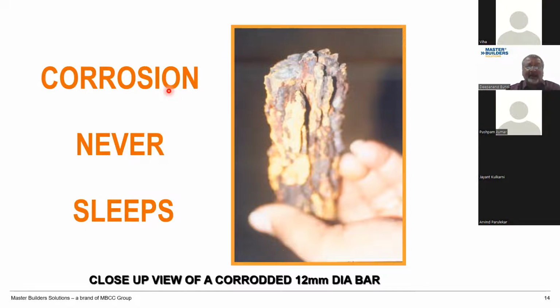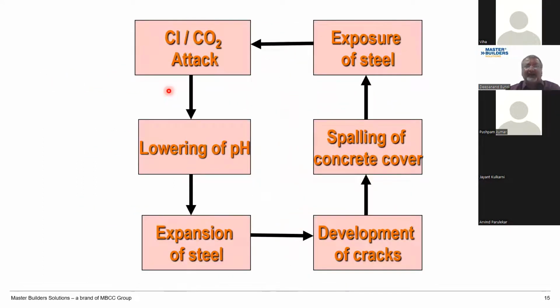That's my hand that I'm carrying it with. And you can imagine what amount of expansion we are talking about. So to just sum it up, we are talking of chloride and carbonation attack happening. It lowers the pH. There is expansion of the steel like you saw in the last slide. Development of cracks happens. Obviously, when there is expansion of steel, the stresses that are developed are going to push the concrete away. Steel has a much higher tensile strength than concrete, so it's going to exert that pressure on the concrete.